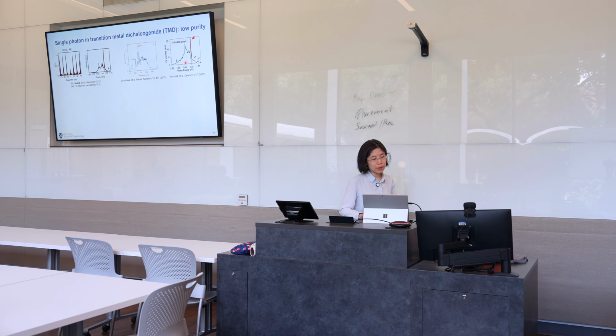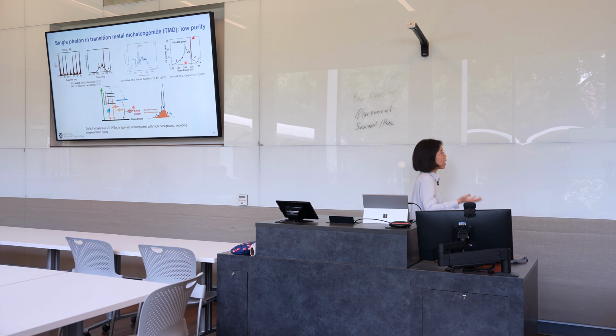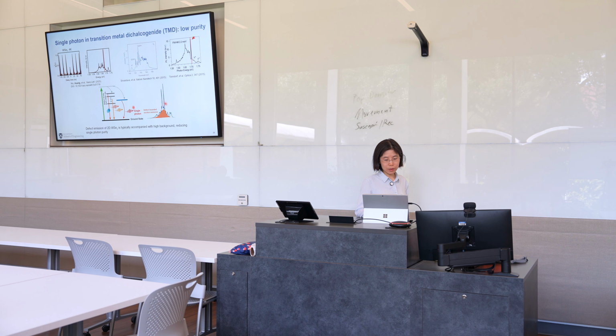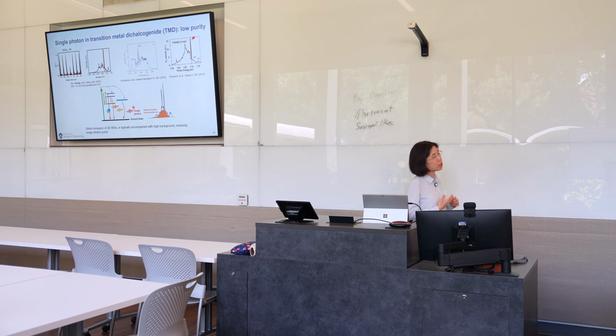The reason we see such a large background is that when you try to excite single photons in tungsten diselenide, you inevitably excite many other processes, such as other defect levels, dark states, trions, and so on. These many processes constitute a large and continuous background. Your single photon process is only one of these many processes. It shows up as a sharp peak, but it's sitting on this large background. So to further improve the single photon purity, we need to suppress this classical background. We developed several strategies to do so.